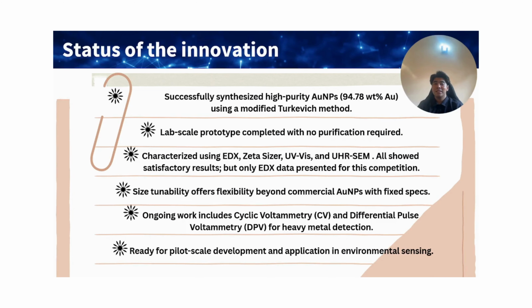We have successfully synthesized 94.78% pure gold nanoparticles using a modified Turkevich method at lab scale without purification. The product has been characterized using EDX, UV-Vis, Zetasizer, and UHR-SEM, all showing promising results. Our next steps involve electrochemical studies using CV and DPV to test heavy metal detection. This innovation is now ready for pilot scale development and has clear potential in environmental sensing applications.